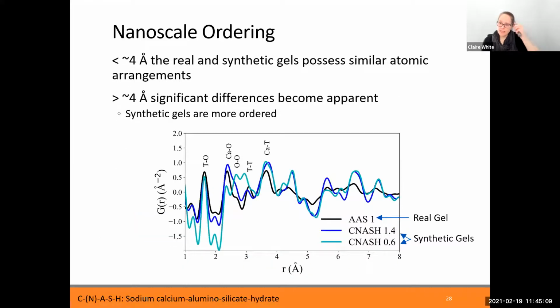The last thing I want to talk about today is nanoscale ordering. So all of what I've shown experimentally was based on synthetic gels. And at the start, I mentioned that it's an assumption that people have that the synthetic gels are representative of the real gels in the concrete. So it's hard to look at this on a Portland cement-based concrete system because you have upwards of 7 to 8 crystalline phases, and then you have the disordered CSH type gel in there. So if you're trying to identify just what the CSH gel looks like in terms of atomic structure, it's very difficult because of all the other phases that give rise to scattering or any kind of bulk technique that you use.